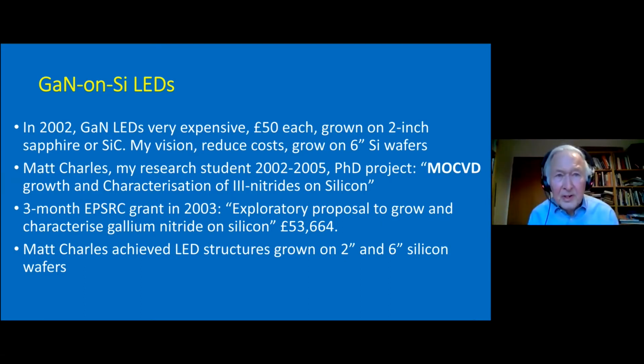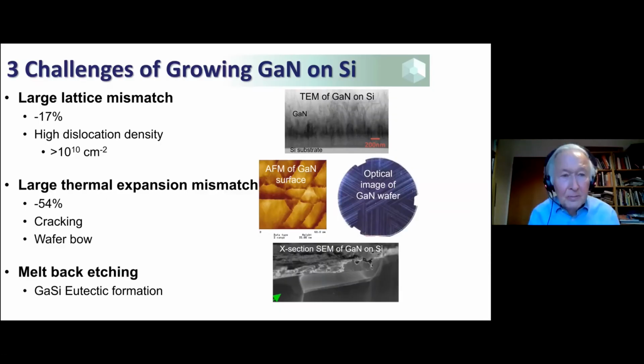So there are 3 significant challenges in growing gallium nitride on silicon. And the first one is there's a very large lattice mismatch between gallium nitride atoms and silicon atoms. It's 17%. And this generates a high dislocation density of greater than 10 to the 10 dislocations per square centimeter. The second problem is an extremely large thermal expansion mismatch between gallium nitride and silicon. It's over 50%. And what happens is you're growing gallium nitride on the silicon at about 1,000 degrees centigrade.